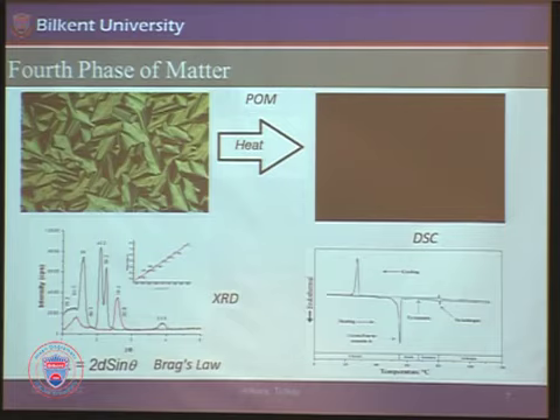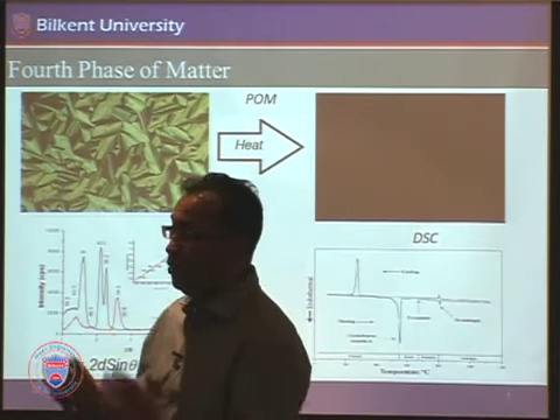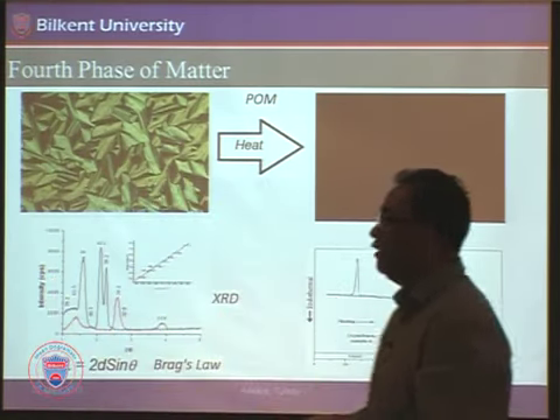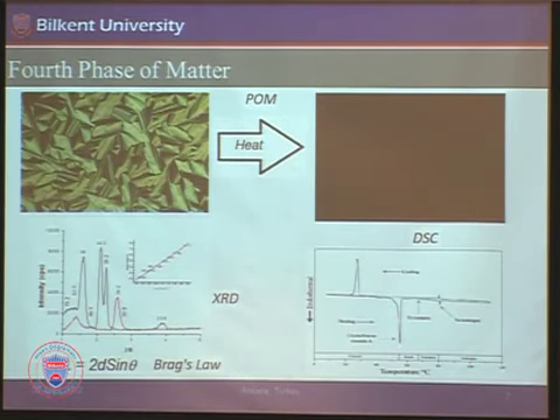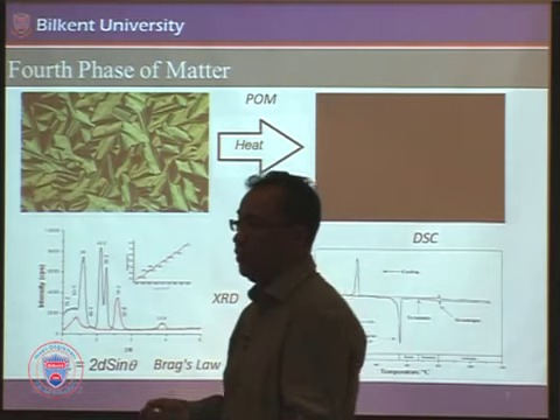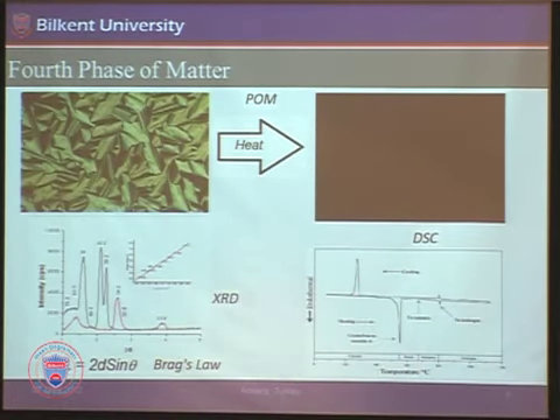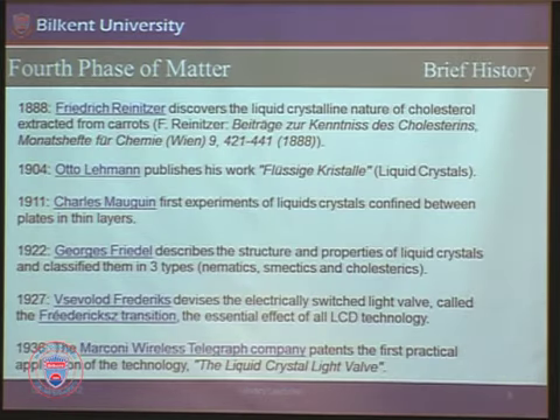You can get lots of detail from these measurements. And DSC, differential scanning calorimetry, also thermally tells you if you have this phase transition, it gives you signals. The position of those signals tells you at what temperature range your liquid crystal is behaving as a liquid crystal. And for application, you don't want your liquid crystal to become liquid crystal at 60 degrees. You want something in this range, something like working room temperature range. That's why not every molecule is doing the trick, but certain types of molecules are useful.